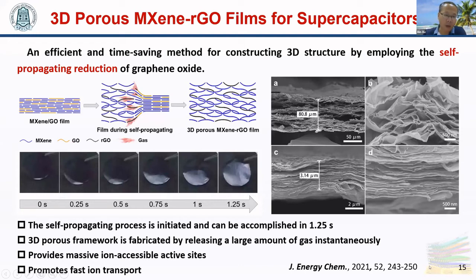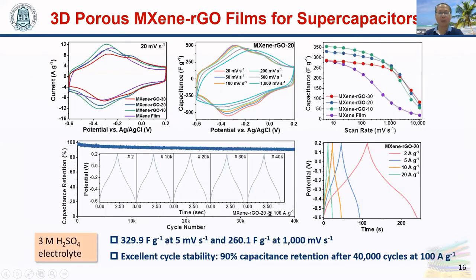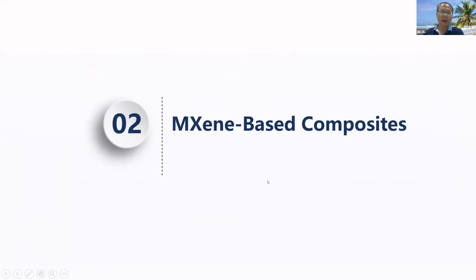During the reduction of graphene oxide, a large amount of gas was released. So the dense structure of the MXene film was opened, creating a very developed porous structure. This structure can provide massive ion accessible active sites and promotes fast ion transport. So being used as electrode materials for supercapacitors, it exhibits very good performance, including high capacitance and very good cycle and rate performance.